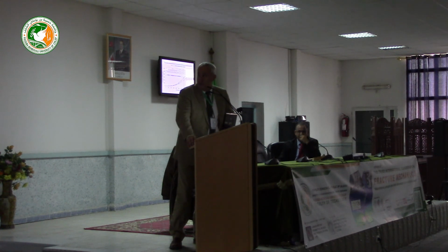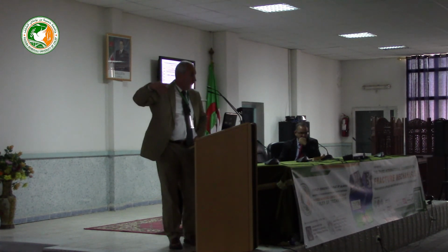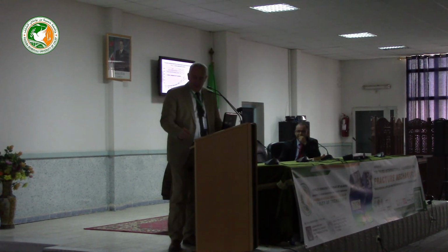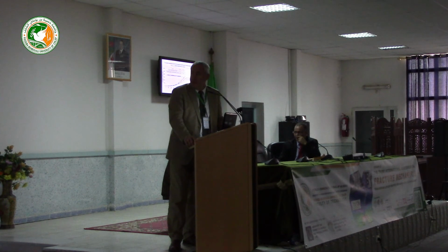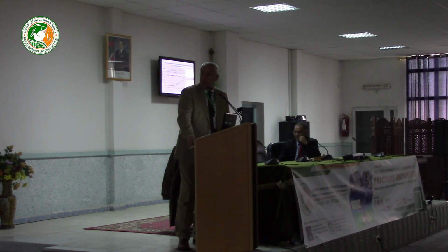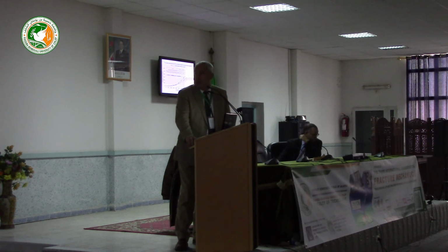So then we increased pressure and calculated K at the crack tips for all specimens, and we obtain these curves here. When we reach this critical value, that's the fracture pressure. And then we compare this to experiments.